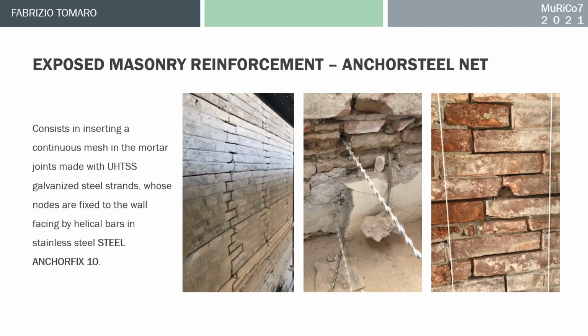Finally, with regard to the external walls of the building, in order to preserve the exposed face, the ANCHORSTEEL net system was used. The structural reinforcement intervention carried out using a reticulatus system for exposed brickwork essentially consists in the insertion of a continuous mesh made with strands of galvanized steel into the mortar joints scarified to a depth of 50-60 millimeters, whose nodes, generally every two, are fixed to the wall face by means of helical bars in stainless steel with a diameter of 10 mm, with fine repointing of the joints by means of M10 hydraulic lime mortar.